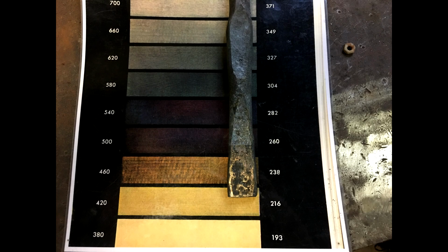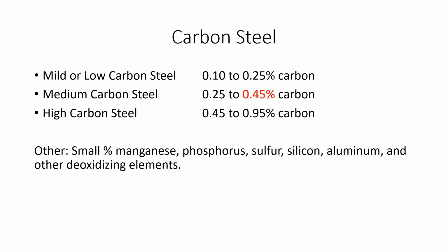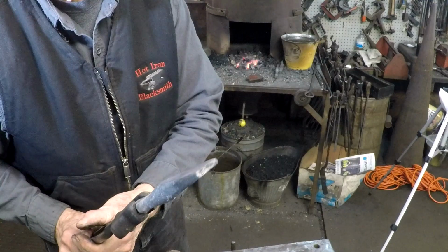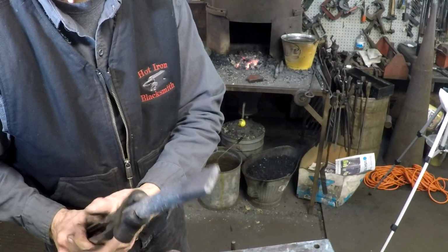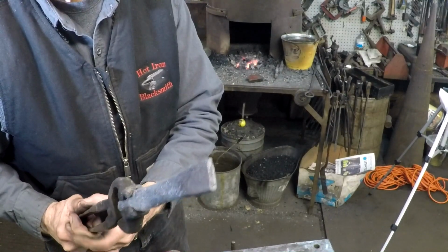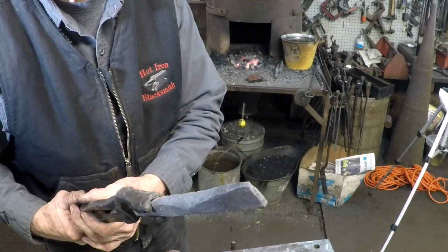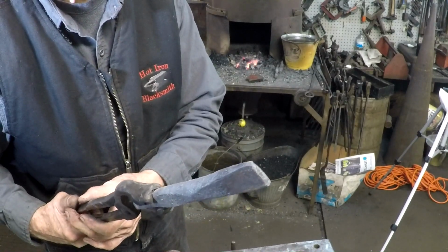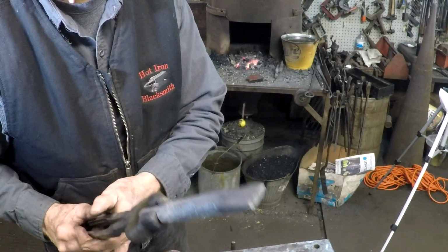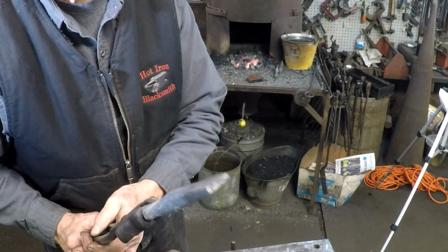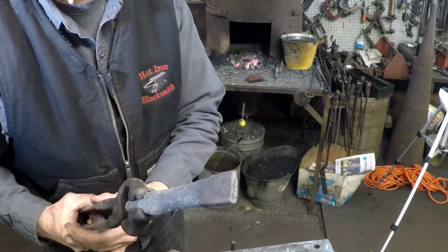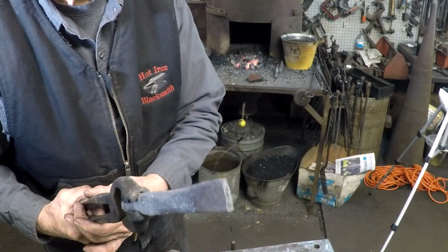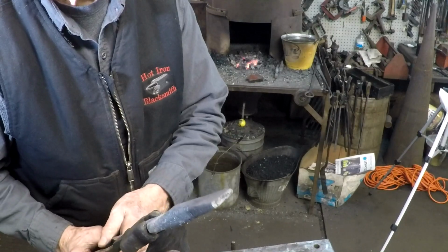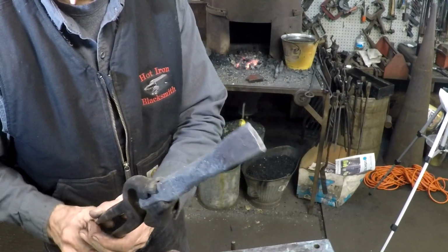Some of the people might say, oh my gosh, don't use water. But this is a relatively mild steel, meaning there's not a large amount of alloy, and it will tolerate the water quench. And the other thing going for us is we don't have any sharp corners or nicks or anything that might cause a stress concentration point, and therefore the quenching in the water is less aggressive in terms of causing stresses and potentially cracking and brittle failure. So there's reasons, and they all work.